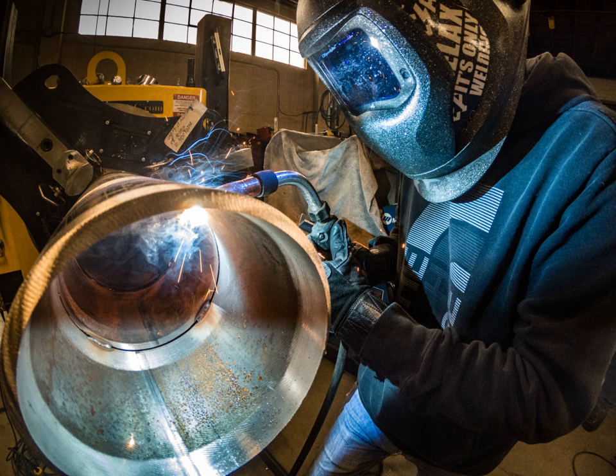Metals, and in particular steels, have a transitional temperature range where above this range the metal has acceptable notch ductility, while below this range the material becomes brittle. Within the range, the material's behavior is unpredictable. The reduction in fracture toughness is accompanied by a change in the fracture appearance. When above the transition, the fracture is primarily due to microvoid coalescence, which results in the fracture appearing fibrous.